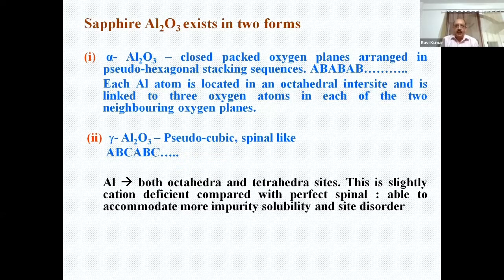So we are talking about two different phases of aluminum oxide. The alpha phase has close-packed oxygen planes arranged in a pseudo-hexagonal stacking, AB, AB, etc. Each aluminum atom is located in an octahedral interstitial site and linked to 3 oxygen atoms in each of the neighboring planes. Gamma Al2O3 is a pseudo-cubic spinel structure. So if we want to grow different kinds of embedded nanostructures, whether my sapphire is alpha phase or gamma phase, depending upon the initial state of my host matrix, I can grow that kind of phase of the embedded structure.